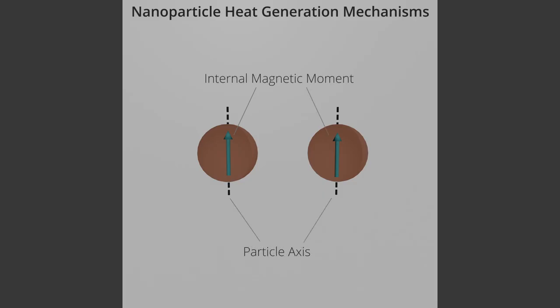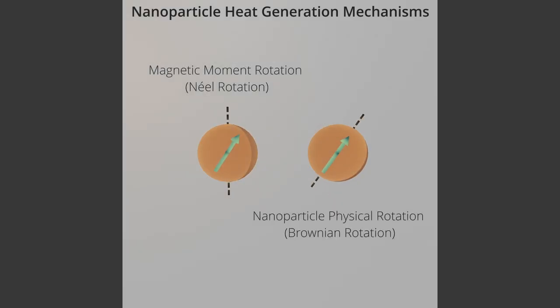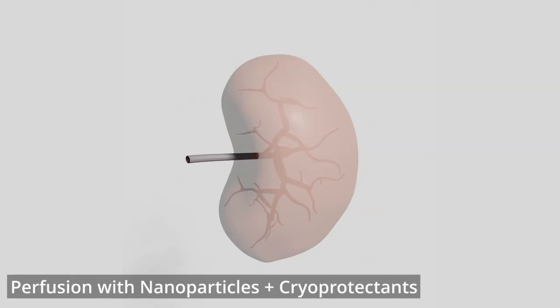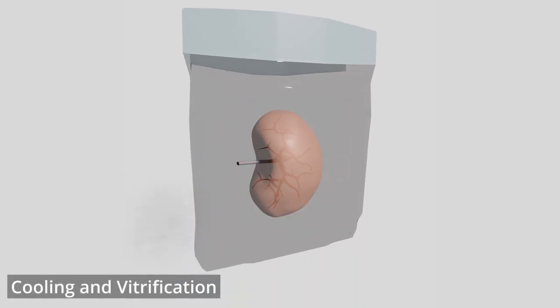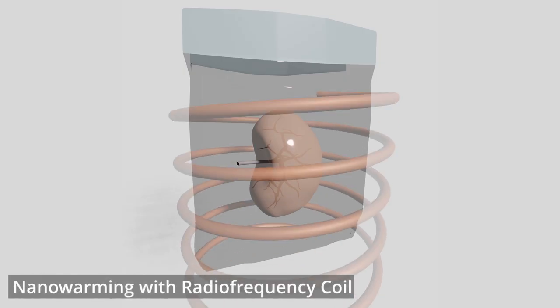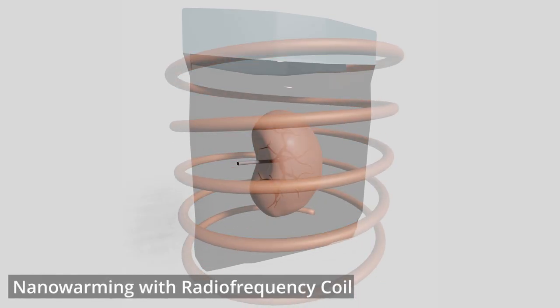The alignment of the magnetic moments of the iron oxide nanoparticles, as well as the physical movement of the particles as they rotate to align with an external field, produces losses in energy as heat. By perfusing iron oxide nanoparticles into organs to be cryopreserved, we can distribute the particles evenly within the vasculature alongside cryoprotective agents, vitrify the organ, and prior to transplant, irradiate the organ with radiofrequency to rewarm evenly.